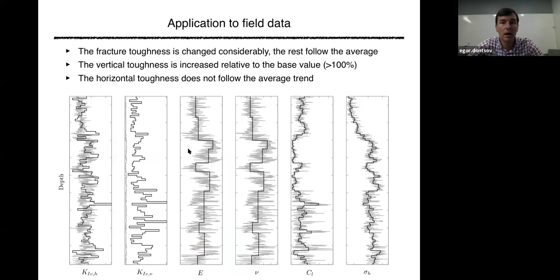Then field data, right? So, just to summarize, what do we learn? Again, we tried to consistently evaluate the effect of high resolution properties on every parameter that enters the hydraulic fracture model. For Young's modulus and Poisson's ratio of elastic properties, we do use backwards averaging, but overall the effect is not as large, right? So even if you use just averaging, you will be off by maybe 10%. It depends on the quantities that you're using.